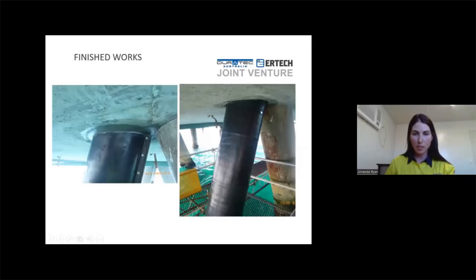And this shows the jacket itself in full. So this is one of the raker piles that were remediated, and this just shows the top, and here are the bolts that go through. You basically wrap it around the circumference of the pile, put the bolts through, and use a hydraulic jack to tighten it. And when you tighten it, the jacket actually pulls down a bit, so you're left with almost 10-20 mil gap from the soffit. So we install what's almost like a sealant on the top, so no water ingress is able to get into that area. So that was that project.